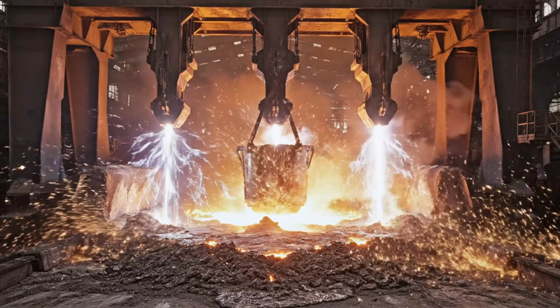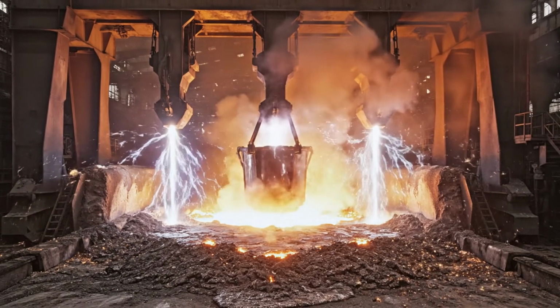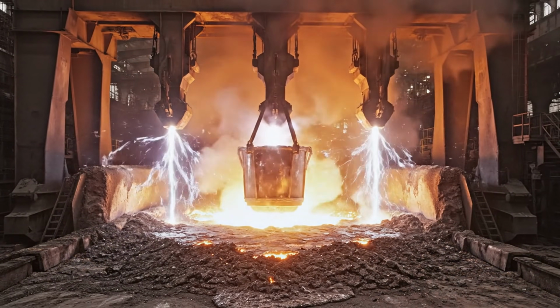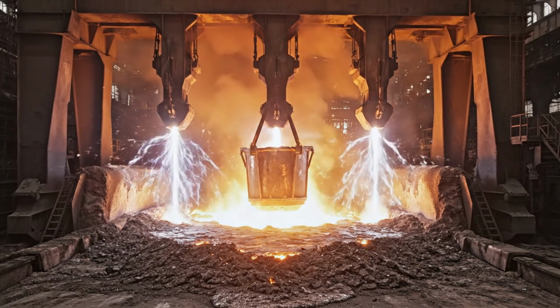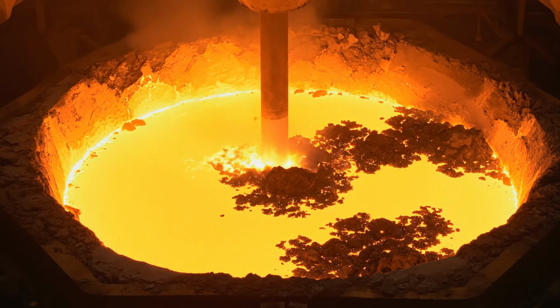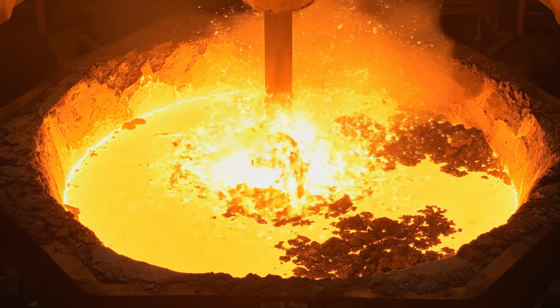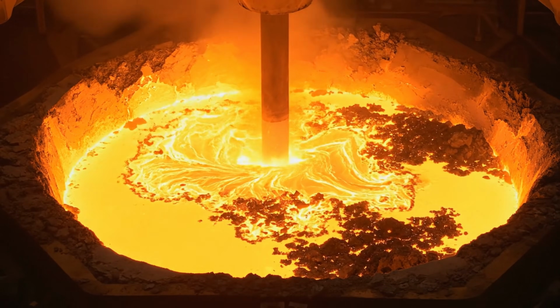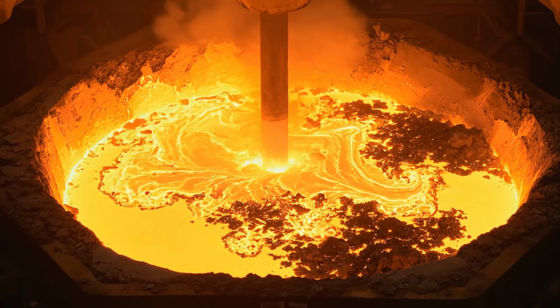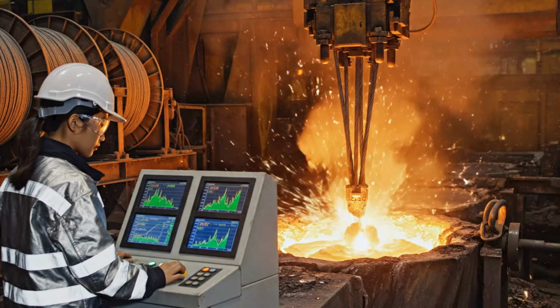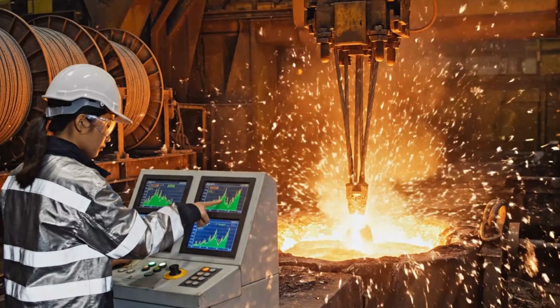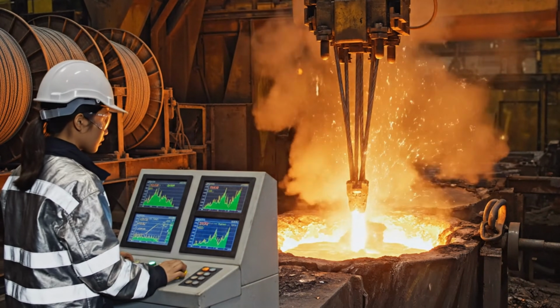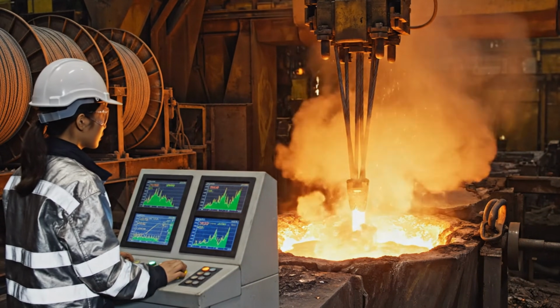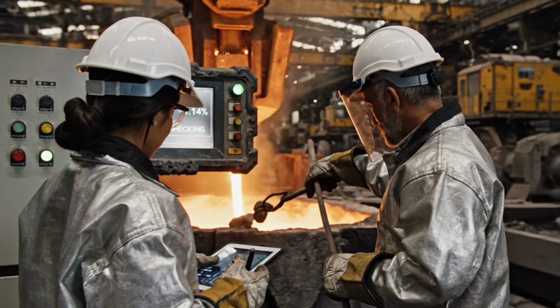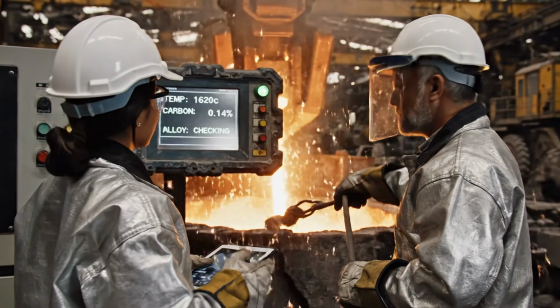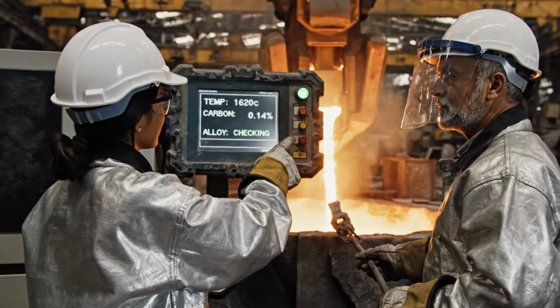The ladle furnace restores temperature and opens the door to much tighter chemical control. Argon stirring helps blend the steel evenly and float inclusions toward the slag. Alloy additions turn a generic melt into the exact steel grade required by the customer. Before casting starts, the plant verifies that the steel matches its final target.